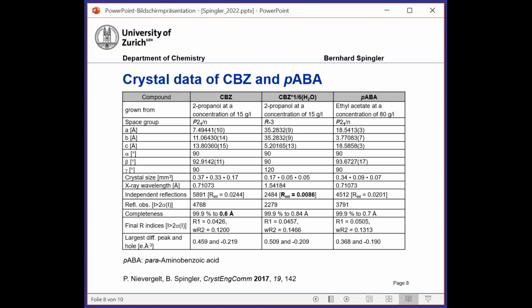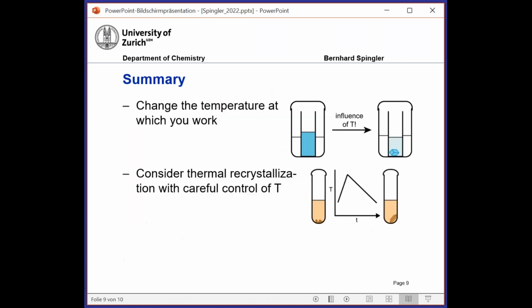On the polymorph which didn't contain any water, which you see in the left column, we could even collect a complete data set up to 0.6 angstrom. And again, this is something non-standard, because obviously for this you have to use the not so powerful Mo wavelengths. You see here also the results from another compound, PABA, which is para-aminobenzoic acid, another very popular compound. And again, here we could grow some very nice crystals.